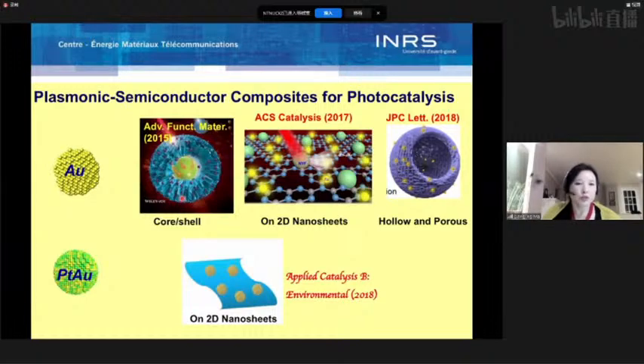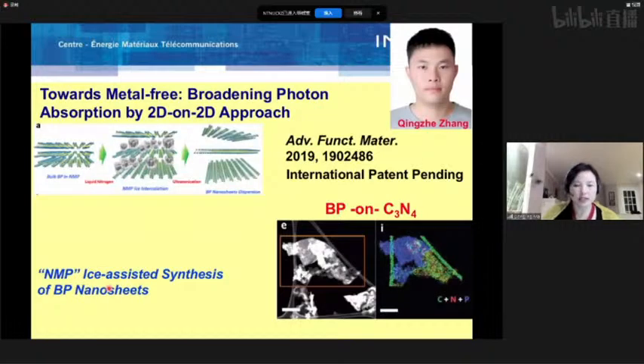So to increase solar photon absorption and to get broadband photocatalytic behavior, we have worked with plasmonic semiconductor nanohybrids. So in these cases, we combine plasmonic materials with the different semiconductors in different configurations. And in this latter case, we also combine the platinum and gold. In this case, we use both plasmonic effect and synergistic alloying effect of platinum and gold for photocatalysis. So in all these cases, we observed the increase of light absorption and also increased broadband photocatalysis. But you can see that these systems involve expensive gold and platinum metals, and for the long run, they are not very sustainable. So that's the reason that why we started to look into cost-effective two-dimensional materials like black phosphorus.